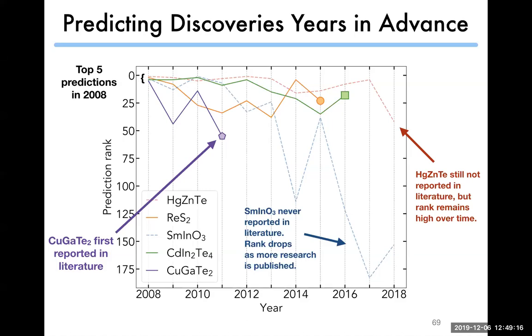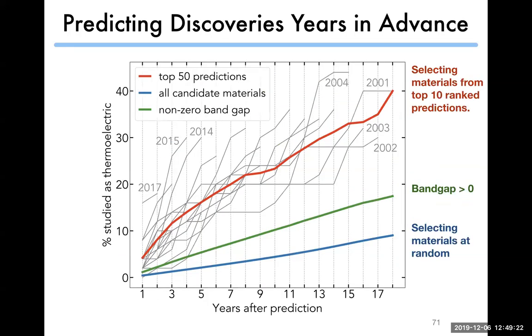But we can repeat this not just for the top five, but for the top 50, and then look and see every year, let's retrain this model. And so this plot shows we start in 2000 with data from before 2000 to 2000, look at the top 50 materials, and then the gray lines, each year we count up how many materials from that set were confirmed to be thermoelectric. So it's just the percentage of confirmed predictions. And then we redo this for every year. So that red line is sort of the average. After 9 years, on average, just about 20% of the predictions from the top 50 are confirmed to be thermoelectric materials.